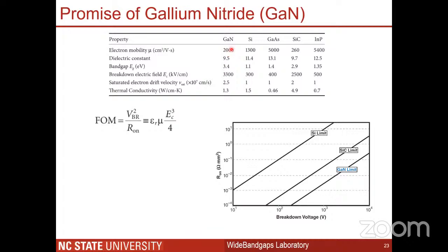So we see that the mobility for gallium nitride has a reasonably high number. It's better than silicon, slightly worse than gallium arsenide. But what comes in favor of gallium nitride is its critical field strength, which is 3 megavolt per centimeter. So it's a large field, and gallium nitride can support such large fields without breaking down. And this number is higher than all these other semiconductors that I have benchmarked gallium nitride against. And this is what lets gallium nitride be very efficient.